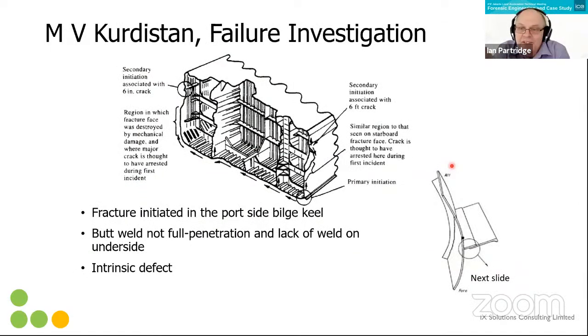The failure investigation involved visual examination, quite a lot of the usual types of testing that they've been talking about: fracture examination, taking samples to do Charpys, and looking at fracture faces. What had happened was the fracture initiated at the bilge keel on the port side. The weld repair was not full penetration, and there was a lack of fusion and an intrinsic defect here, not overly large. It reached a critical size and started to run as a brittle fracture, running out of here and then going up the sides. This is the primary initiation, and the cracks ran this way. There was a secondary initiation over here.